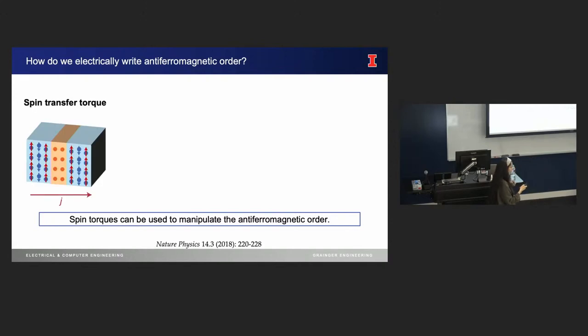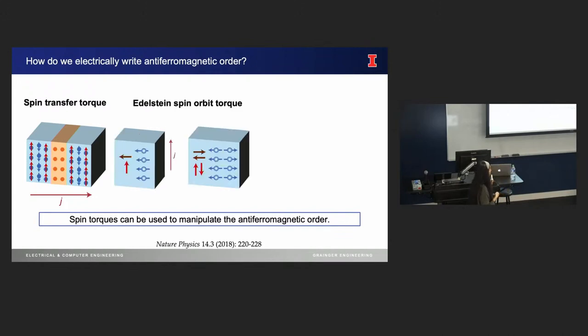Let's go back to my favorite device, the tunnel junction. Two antiferromagnets with an MgO barrier in between. So the idea is, you pass a current and then flip the magnetization of the second electrode. This does not happen in reality. No one has experimentally demonstrated it yet. The reason is that for this phenomenon to occur in antiferromagnets, you need commensurate heterostructures. You need perfect epitaxy, and you need ballistic transport of spins. Those are very challenging to achieve in experiments.